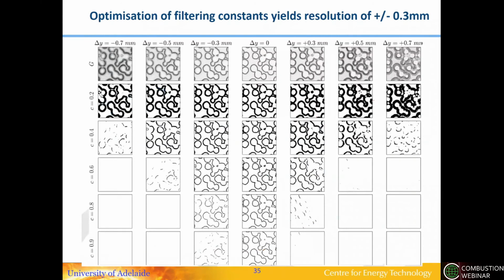And this also illustrates that the depth of field depends on the constants you use in the algorithm. It shows that the out-of-focus particles can be eliminated to up to plus or minus 0.3 millimeters. So the net spatial resolution in that dimension is about 0.3 millimeters.